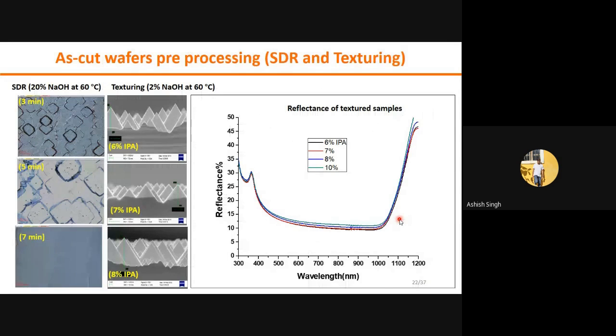So in continuation of that, we took the as-cut, as-received wafer from the industry, and we did the saw damage removal of the silicon wafer, and we found a planar surface of the silicon wafer in 7 minutes. After that, this SDR sample we moved for texturization with 2% NaOH, and we measured the reflectance of the samples, and we found the reflectance is coming in the range of 10% in the visible region.